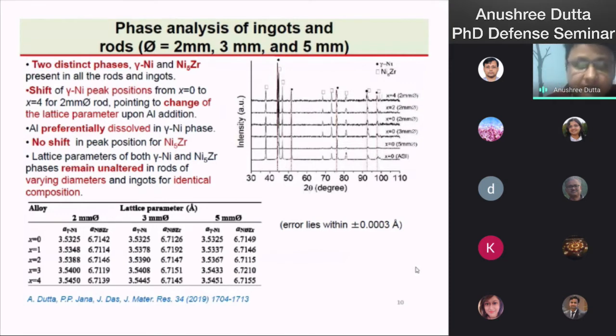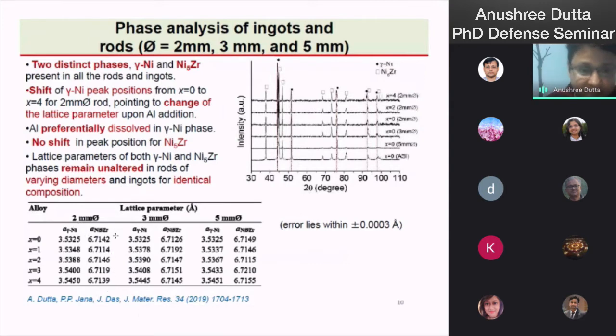with the addition of aluminum content, whereas there is no change of peak position of Ni5Zr upon aluminum addition. The peak positions of gamma nickel and Ni5Zr remain unaltered with change of casting thickness from ingot to 2 millimeter diameter rods. The lattice parameter, as estimated using Rietveld refinement analysis, is given here. We can observe an increase of lattice parameter with aluminum content for the gamma nickel phase, whereas there is no change of lattice parameter for the Ni5Zr phase, for 2 millimeter, 3 millimeter, and 5 millimeter rods.